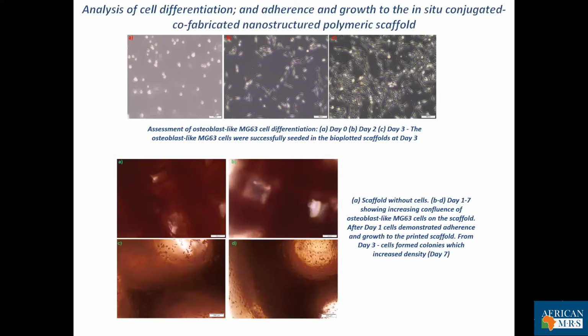Very important is the observed cellular differentiation, adherence, and growth of your osteoblasts following incubation with your scaffold. So basically, after 1 day, the cells already demonstrated adherence and growth to the bioprinted scaffold, and from the 3rd day, you can see that the cells are forming colonies, which increased greatly in density at day 7 already.